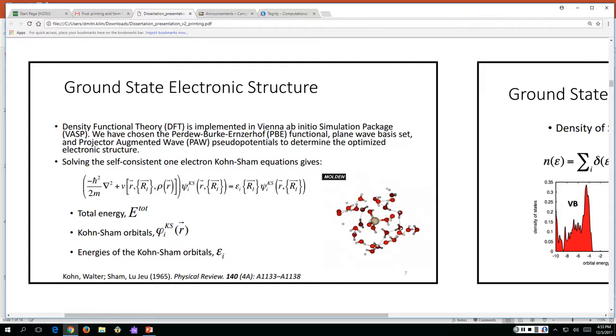Okay. And so the second thing that we kind of want to mention, and also alluded to in the Kohn-Sham energy fluctuations, is the fact that band gap energies are going to change as a function of size within the material. And so what I'm showing here are three density of state plots for the silicon systems. So you can see with the populated and unpopulated states that the band gap decreases as the material gets bigger, which is something we would expect. And so the band gap values themselves are listed in the left table, going from 3.6 down to close to 2 electron volts.